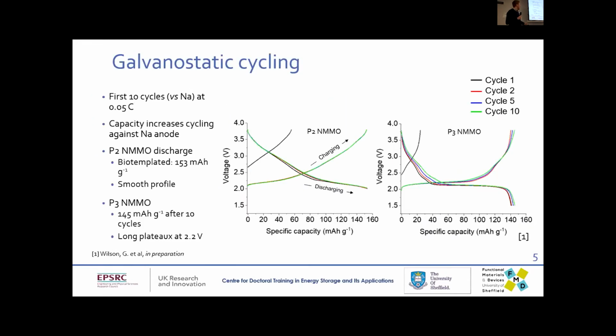So here's how they perform. This is cycling these cathodes on their own against a sodium metal anode. They're pretty stable, as you can see, so going from cycle 1, which is the black line, to cycle 10, which is the green line, the capacity doesn't change very much. It actually goes up because we're cycling against a sodium metal anode, so there's an infinite supply of sodium within the cell. But suffice it to say, it's very stable, and about 150 milliamp hours per gram, slightly lower than reported, but I'm going to chalk that up to me needing to finesse the cell assembly slightly. So yeah, stable, which is good.